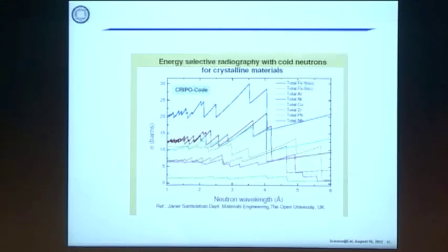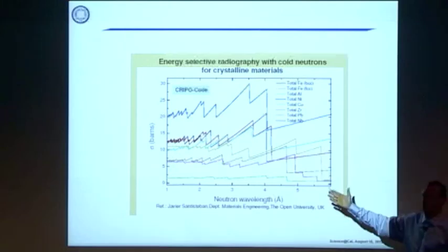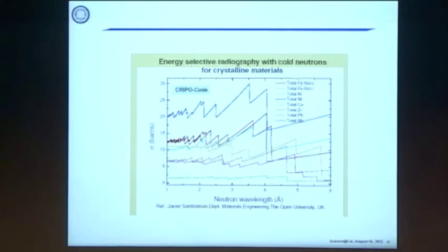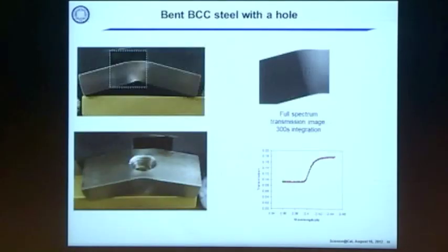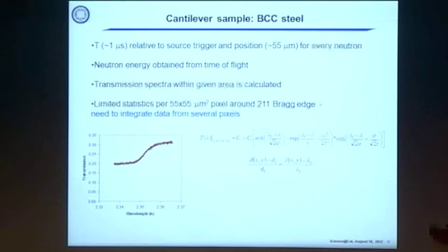And it changes by a tiny amount, but this amount is actually very challenging to measure. They're changing by milliangstrom. So the wavelength would be, let's say, 3 angstroms, and it changes by a milliangstrom. But if we can measure that accurately, we can find out what the strain is at that particular point. And of course, for that, we need to know the sample unstrained first, and then we measure strained ones. And the challenge here is that the source itself is broad enough in the beginning, so we're not getting milliangstrom accuracy, but we do mathematical tricks by doing fitting, and we can reconstruct data with milliangstrom accuracies.